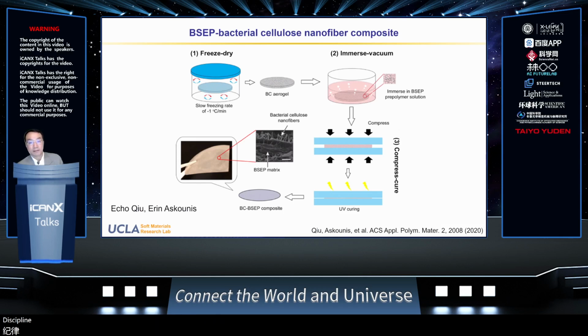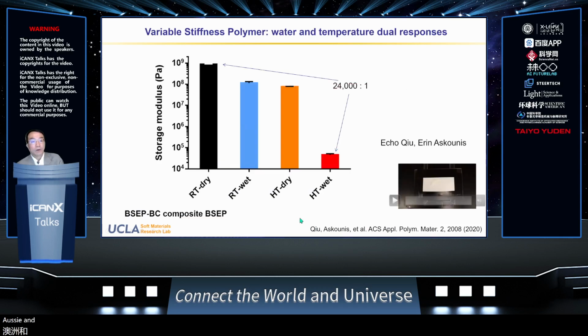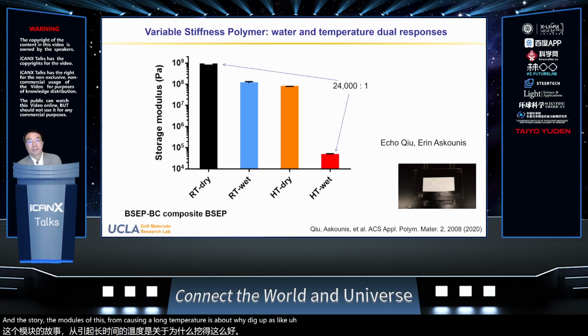BSEP resin and cure it. So the resulting sheet is the BC-BSEP composite, and it looks paper white, like the one shown in the lower right image. And the storage modulus of this composite at room temperature is about 1 gigapascal, like a typical stiff plastic. And when it's exposed to moisture, the BC part softens.